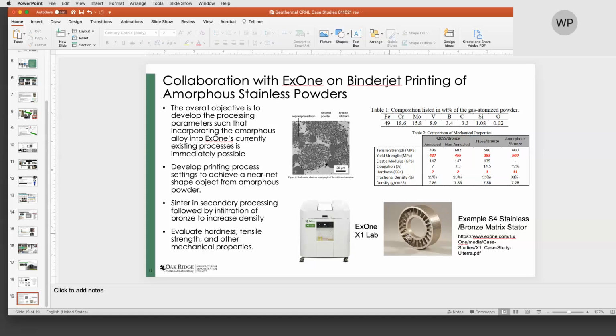One that has been tried out and made as an example by one binder jet company, ExOne, that we have had a long collaboration with. They did a stator where they used stainless and a bronze matrix, and by doing that would get sand particulates or silica into the softer material. It would create a hard sacrificial layer that would actually improve the overall performance. In fact, if you go to the X1 site, you can see a case study on this.